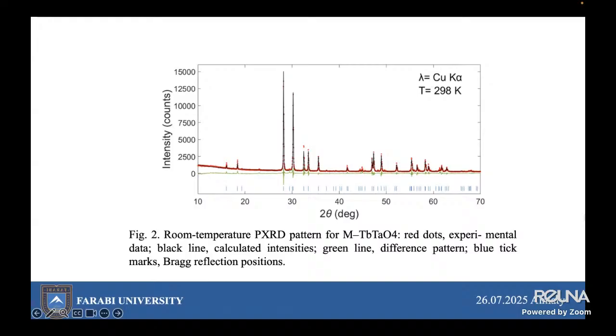And here also, the unit cell parameters and the terbium and tantalum atomic positions were refined, while the atomic positions of the oxide ions were fixed based on the neutron diffraction data from previous experiments.